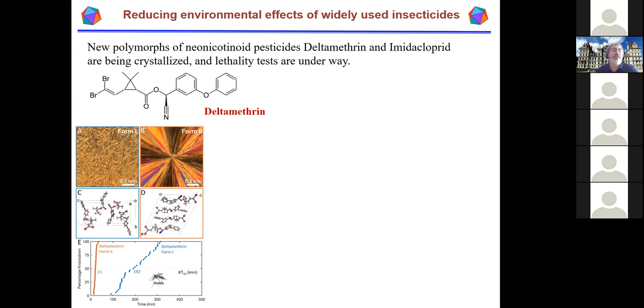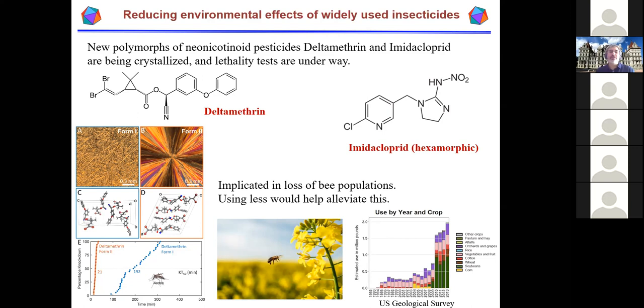And so for imidacloprid, this is now a brand new study because this thing is hexamorphic. So there are like six polymorphs that they've been able to find. And right now they're doing lethality tests to see how these different polymorphs perform. And the interest in this, obviously, is that the use of these pesticides does actually cause loss, for example, of bee populations when they're overused. And over here on the lower right, this U.S. Geological Survey shows the use of this imidacloprid over the years, and just how in the last decade the use has really spiked. And you now have enough of this out there that you can see the effect on honeybee population. So if you can use much less of it, you can help alleviate this problem while still having a very effective pesticide. So this idea of exploiting polymorphism in agrochemicals, I think, is a very, very fascinating thing.